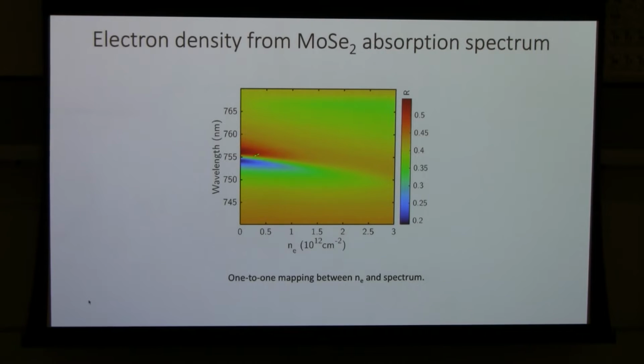The same procedure can be done for the MoSe2 layer. This is the optical spectrum as a function of electron density. Again, if there is no electron density, there is a very strong resonance corresponding to excitons. When you have increased electron density, the exciton resonance gets reduced and shifted, and then the trion resonance emerges. Can I ask a question?